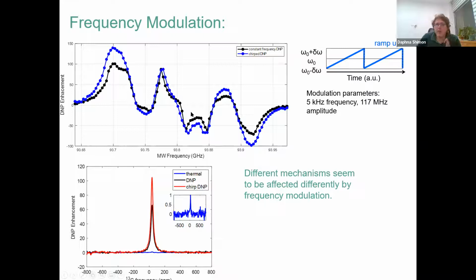So instead of irradiating directly at one frequency position and then measuring enhancement, which is what we do normally in DNP, you can also irradiate on a range of frequencies. Here we use a ramp-up shape irradiation frequency with a 5 kilohertz frequency modulation, which means that it changes frequency at 5 kilohertz. And the amplitude of the change is about 117 megahertz. The first thing that we see when we turn on this modulation is that the enhancement goes way up, and now we have more than 100-fold enhancement of carbon at room temperature. And remember that we don't have high power, so I think we could get even higher.